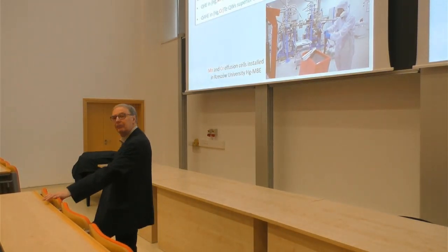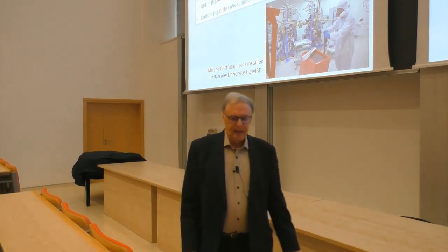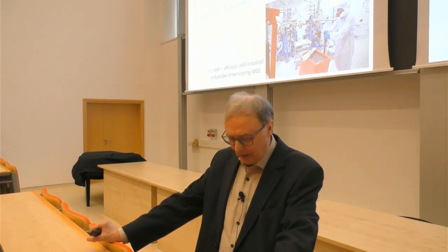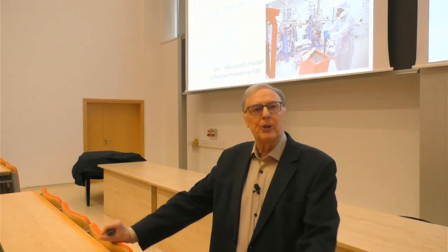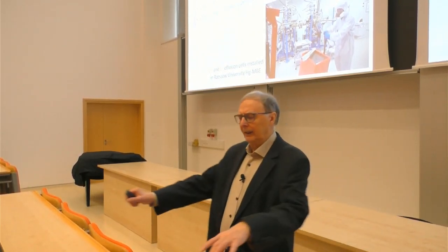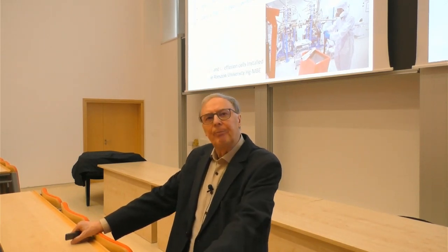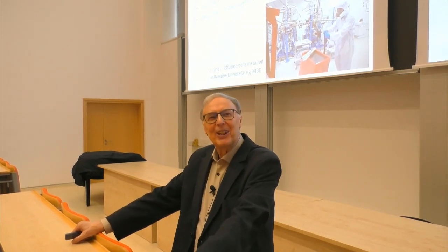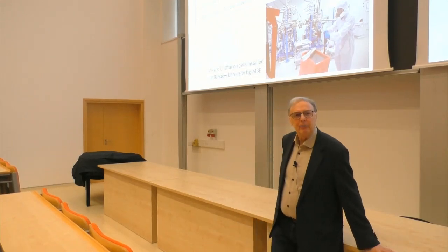quantum Hall effect. In the case of chromium, we want to have ferromagnetic interaction, and chromium does not enter so easily. So this kind of game, which we will start, is to find conditions under which chromium enters. The calculation I did for 3% of chromium should be okay, but this is not yet done. I know that other people also think about that, so we have competitors, but I think 3% would be okay.